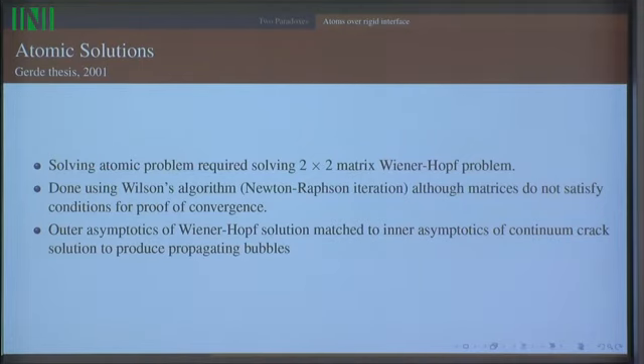Now, we were worried because the conditions for Wilson's algorithm, I believe, are that the matrix involved be Hermitian. If there's any proof of convergence, our matrices are not Hermitian. And so it was a bit touch and go and depended upon skillful choice of initial conditions. But eventually we did manage to have successful factorization of thousands and thousands of these Wiener-Hopf problems, which you can verify after the fact if you get them.